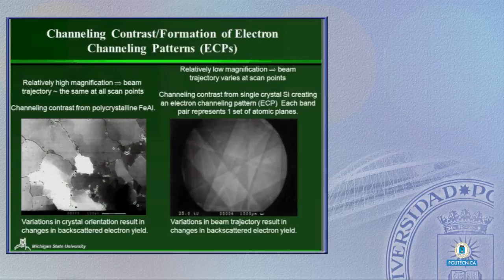If we take a typical polished polycrystalline sample and we look at it in typical backscattered mode, and if we don't have other things going on like phase contrast and things like that, grains with different orientations are going to give us different backscattered intensities. So as a result, we can see the grains quite easily. You can even see little details like the subgrain boundary along here, and there's another one there, that is indicative of this change in backscattered intensity or backscattered yield as a function of the crystal orientation.